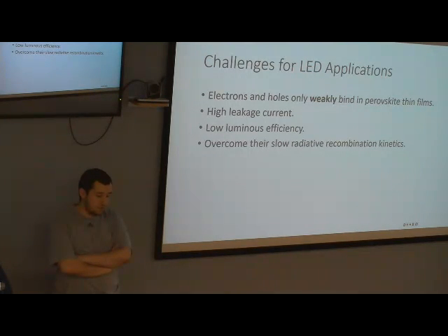That goes back to, well, current materials don't have the highest external quantum efficiencies. In the recent paper that I'll be talking about later, they have an external quantum efficiency of 14.3%. So 14% is not impressive by any means, but it is comparable to conventional LEDs on the market. So that's what I mean by low luminous efficiency. It's not high, but it's working.